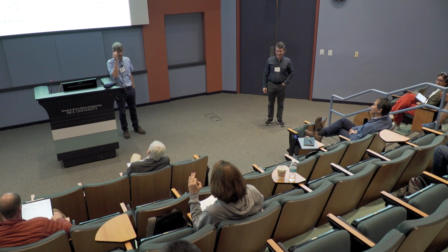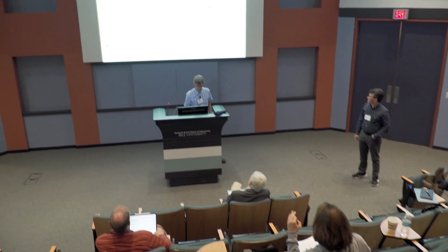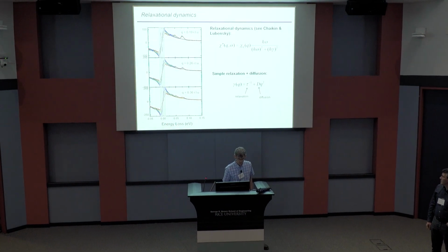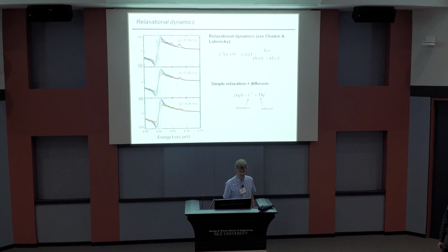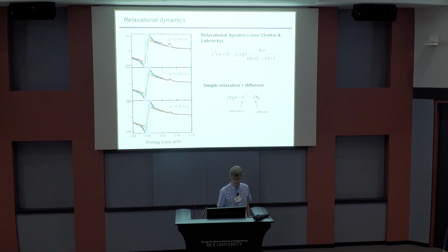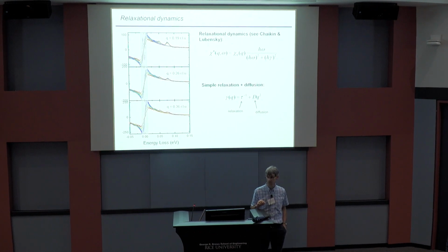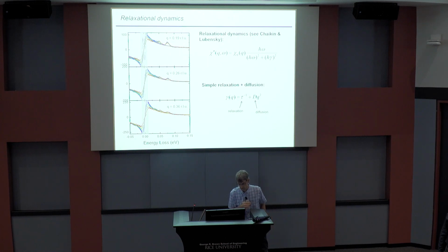So I'm confused. In which frequency range do you see that relaxation of dynamics? How low is the frequency? Okay, it's below, compared to kT. So kT ranges from 25 meV down to around 10, and then we're looking at sort of minus 25 to 25, minus 50 to 50 meV. This is the energy scale here. So the energy scale is not much smaller than the temperature.